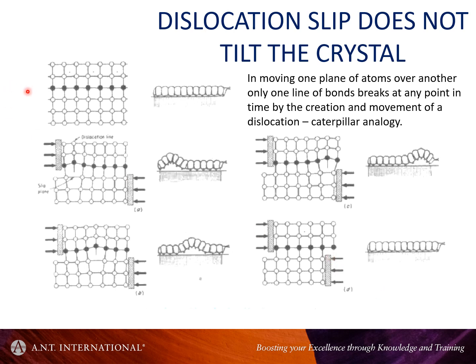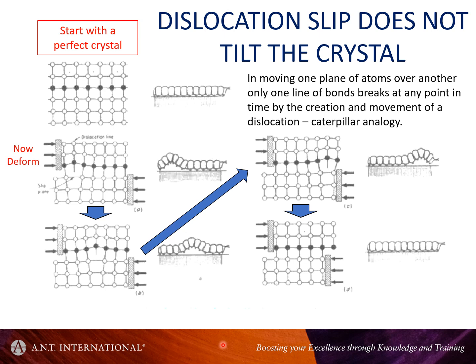So that's typically what happens in the movement. We start with the perfect crystal, we start to deform, and we go from there to there to there. So that's the simplest way to think of dislocation slip. Take note, this is something that might come up in your studies, you may come across it a lot. The deformation by dislocations doesn't change the arrangement of the atoms. There's no orientation change here. Ignore the fact that these are black. It's just a way to note where we have this separation of the two halves of the crystal. But the atoms here are the same orientation. Dislocation slip does not change the orientation of the crystal, certainly not at the location of the slip itself.